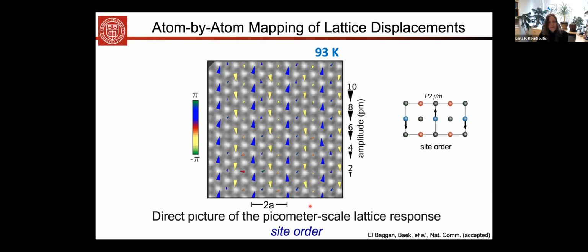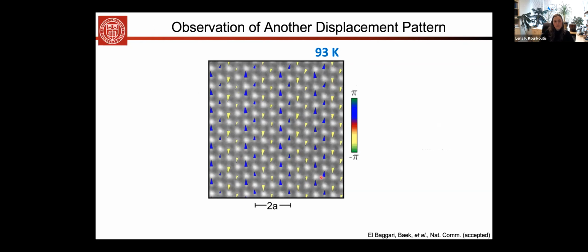So this is actually a model that is well understood from the 60s, and now we provide this real space picture of the site-centered symmetry. Now, that itself would be interesting, but what's more interesting is that if we go to a different part of the sample, we see an entirely different symmetry. And so here you see an up, up, down, down, up, up movement. And that pattern will remind you of the bond-centered order, with one small caveat, which is that the displacements here should be the same, versus in the experiment, where you have clearly one side that is stronger displaced than the next side.